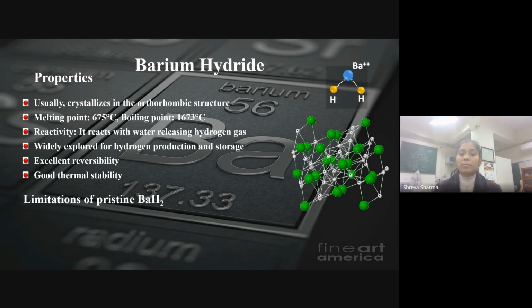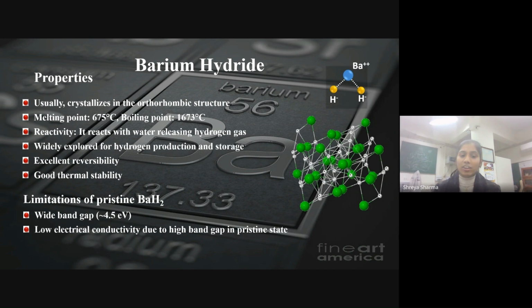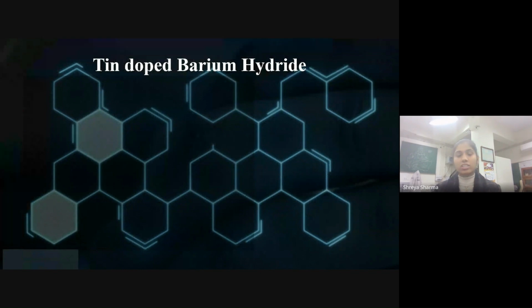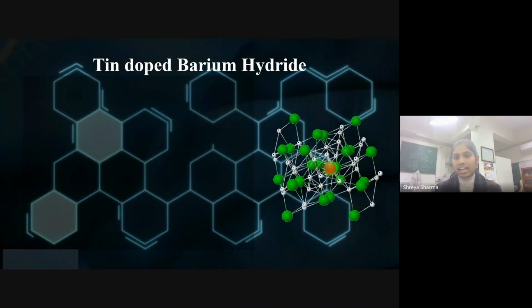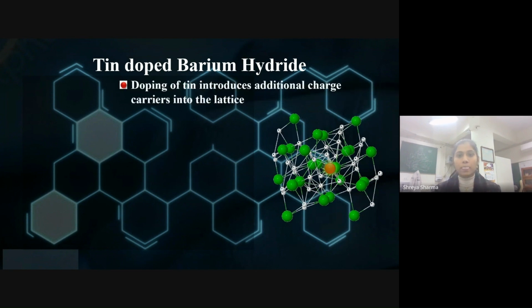However, there are some limitations of pristine barium hydride. It has a wide band gap, approximately 4.5 electron volts, and low electrical conductivity due to the high band gap in the pristine state. Thus, it affects its direct use in electronic and electrical applications. To overcome these limitations, I have doped the barium hydride with tin, as can be seen here in the figure.